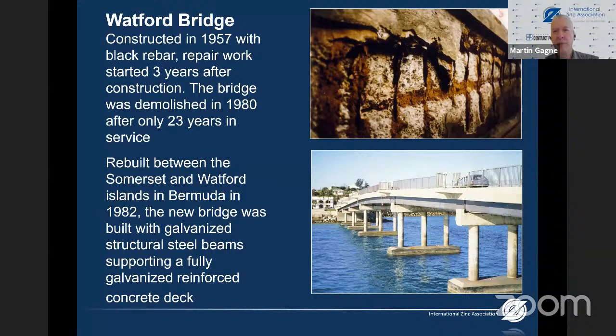This is a bridge example from Bermuda, a marine environment, very corrosive. The top photo shows the original concrete bridge built with black rebar in 1957. Repair work started 3 years after, and the bridge was actually demolished in 1980 after only 23 years of service because it was significantly corroded and not structurally sound. The bottom photo shows the new replacement bridge, which was built in 1982.